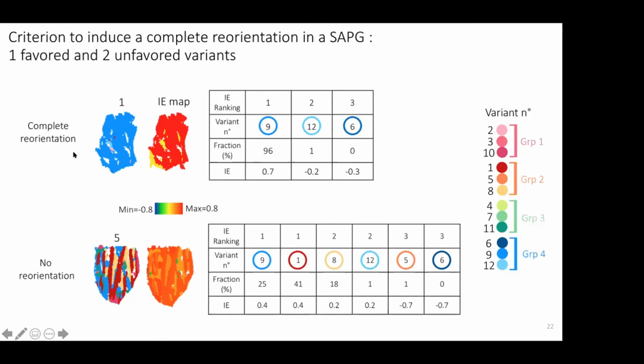So in the first one, we can see that after deformation, the variant that remains is variant number 9. And because we know that before deformation we had complete self-accommodating groups, we should have had before deformation also variant number 12 and variant number 6, because variant number 9 is in group number 4. So before deformation, we had variant number 12, variant number 6, and variant number 9. And after deformation, we just have variant number 9. And if we take a look at the interaction energy, it seems to be true, because the variant that grew at the expense of the others is the one that has the highest interaction energy.